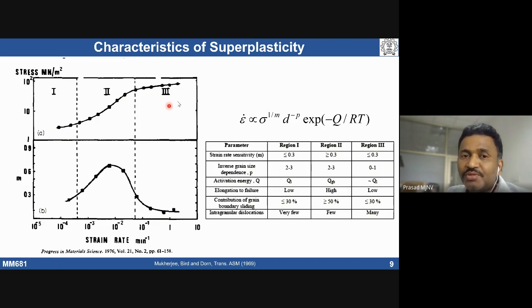Okay, so typically this region 3 is associated with the dislocation creep mechanism, because of higher n values. m is low means n value is going to be higher. We do see a lot of dislocations under dislocation creep activity.